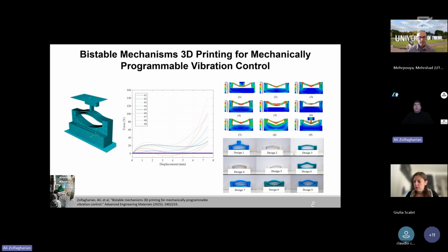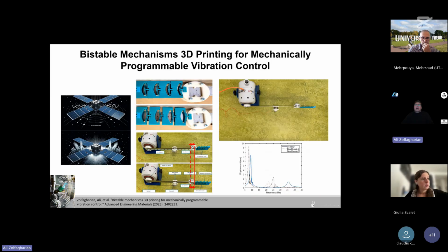And after trial of several designs, we could come up with designs that achieve bistability. One of the issues here was the boundary conditions, because of the defects that occur during 3D printing, we needed to come up with a very optimized way of 3D printing this sort of bistable mechanism. Then few of these designs reached that bistability. We then show the application of this bistability by stacking this bistable mechanism into each other. As you could see, we could have some sort of the displacement that was needed, and with changing of this displacement manually, it was not like a 4D at this stage, but it has potential for 4D printing in the future direction.